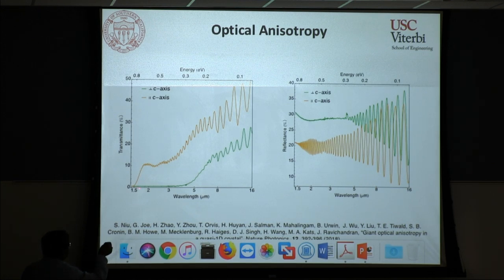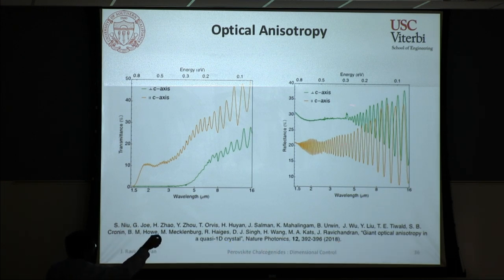And just like the theoretical predictions, you could see that the absorption edge is very different along the two different directions. And consistent with the absorption edge from the transmission spectra, the reflectance spectra also show the vanishing Fabry-Perot fringes at the right location where you hit the absorption edge. Okay, so these two things are very consistent, and using these fringes we can get an idea of the index and also the thickness of the material. We can't distinguish the two exactly, but we have a starting point to work with.